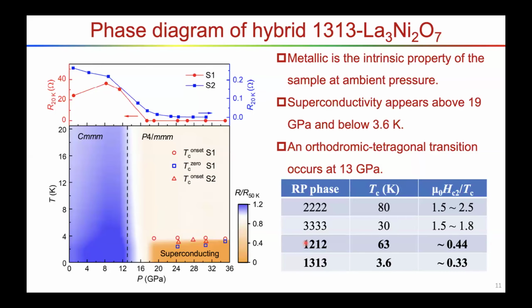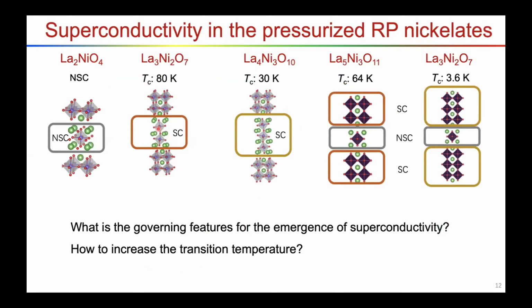actually, we can claim the single nickel-oxygen-6 layer is insulating. It's not superconducting. Only the bilayer phase or trilayer phase is superconducting. So now we know the superconductivity in different Ruddlesden-Popper nickelate phases.